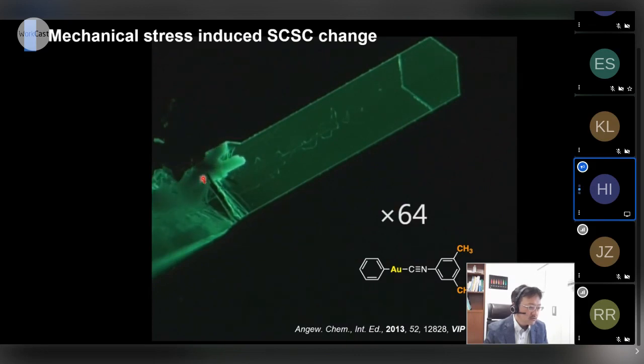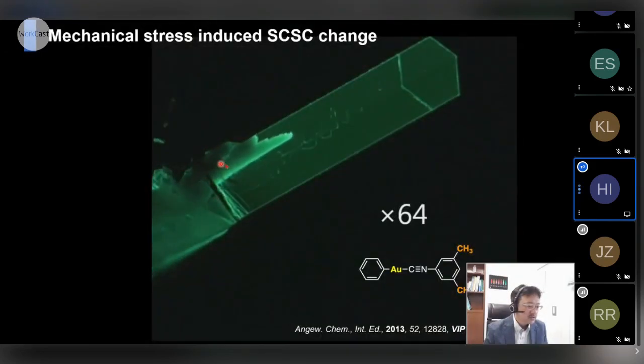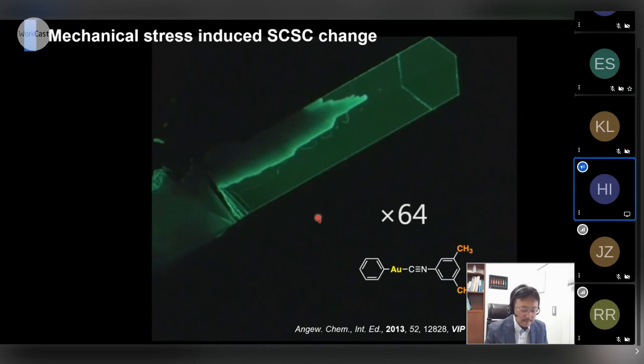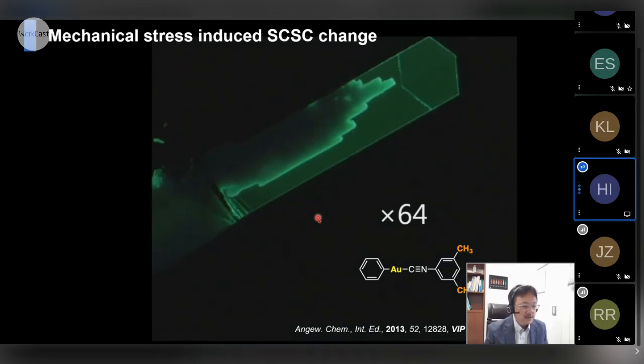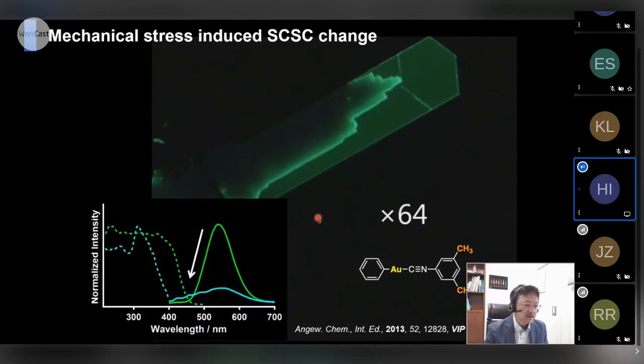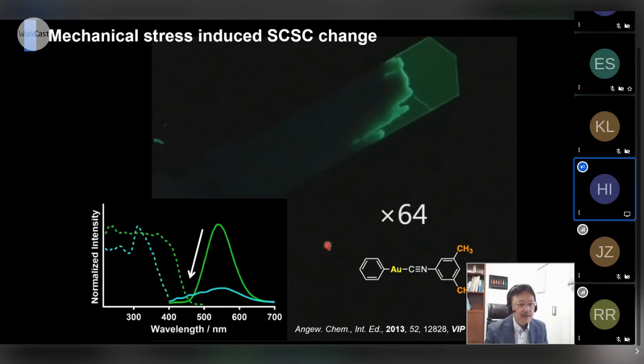As you can see, a single crystal phase emerged from this part, and this new phase developed through the crystal. It is interesting to see that growth in this direction is very fast and in this direction is not so fast. But after several minutes, this phase change was completed, giving a new blue-colored crystal structure. This structure shows blue-shifted emission.